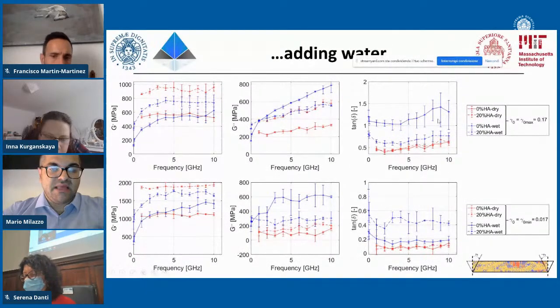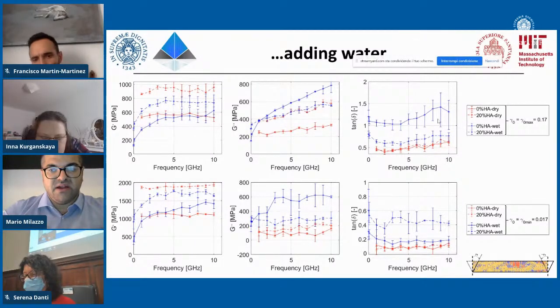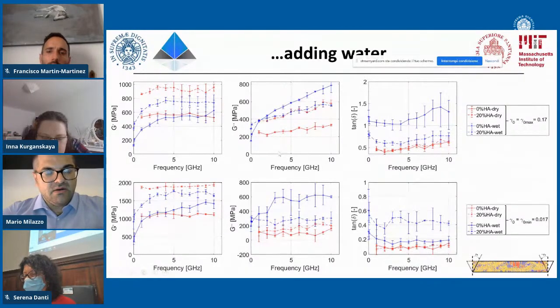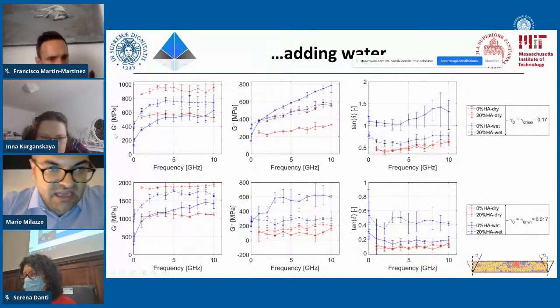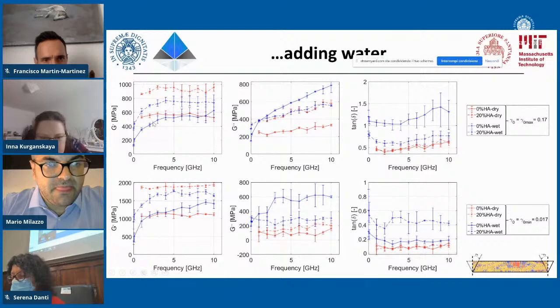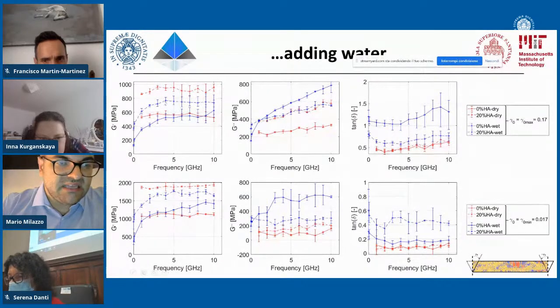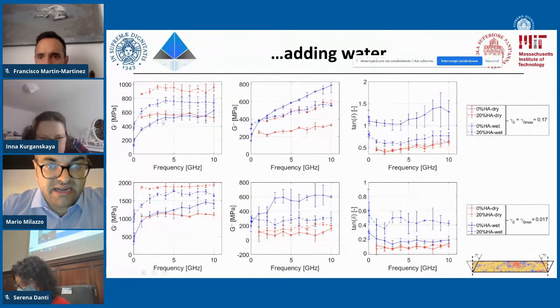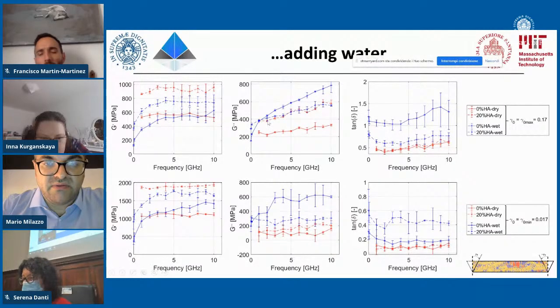Now, adding water, what happened? What happened when we added water to the compound, because we saw something related only to the dry fibrils. So adding water, we are not seeing any specific change for the elastic component besides a progressive saturation that is below 3 gigahertz. Instead, the viscous behavior is significantly affected, and you can see that especially at high frequencies we can reach very high values.